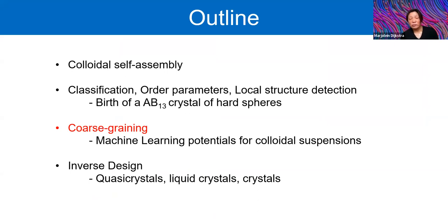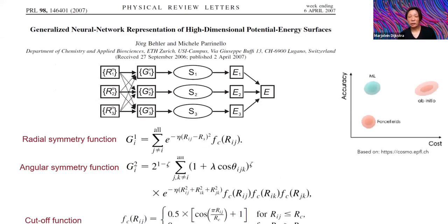So we can also use machine learning to coarse-grain systems. This is really inspired by the work of Behler and Parrinello, where they showed that one can do either electronic structure calculations or ab initio calculations. This goes with very high accuracy, but it is extremely computationally expensive. If we use classical force fields, then the accuracy is much lower, but it is much faster. If we use machine learning potentials that are trained on electronic structure data, we can achieve an accuracy that is similar to the ab initio data, but with a speed that is really comparable to the force field calculation.